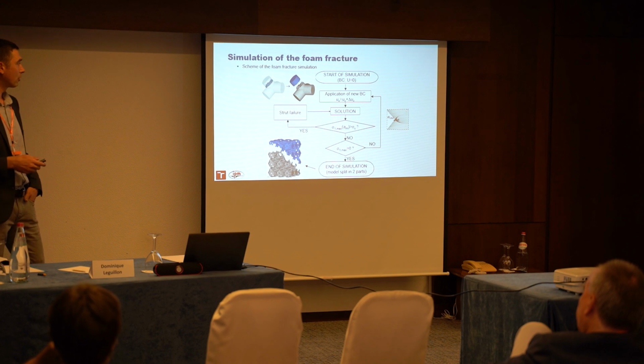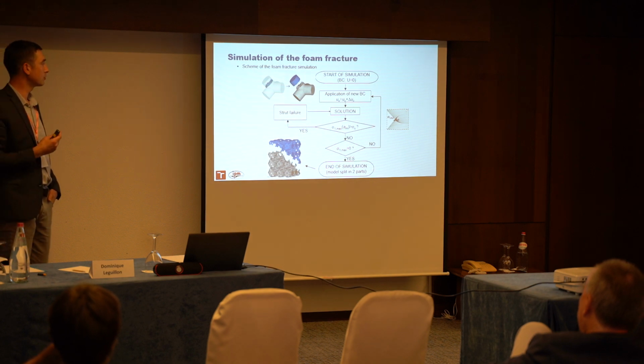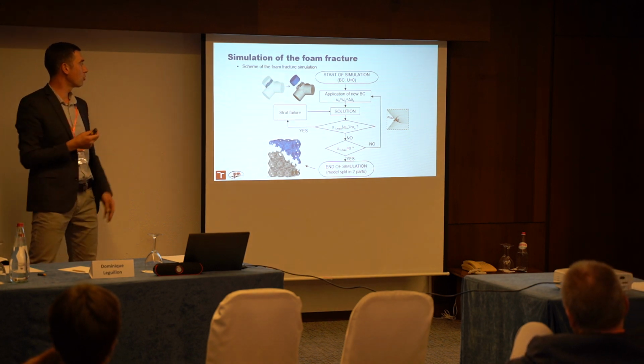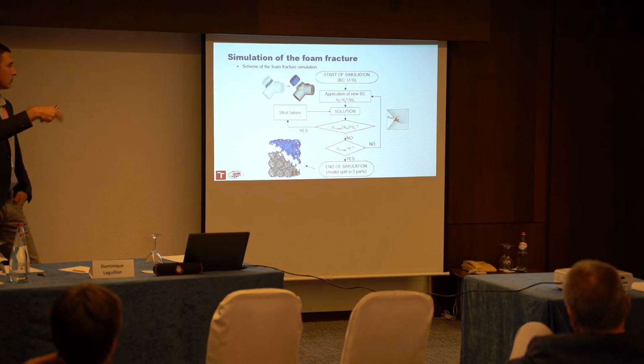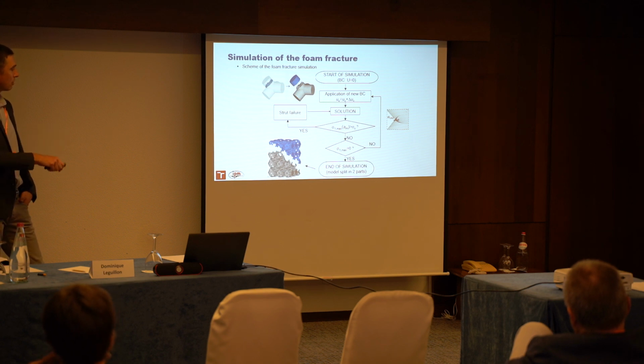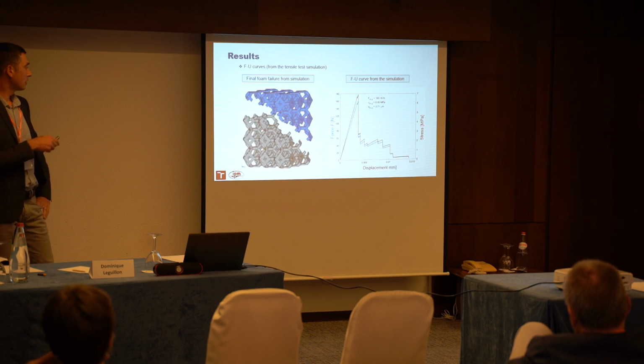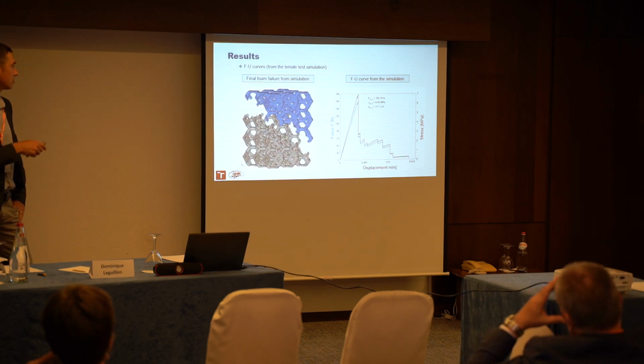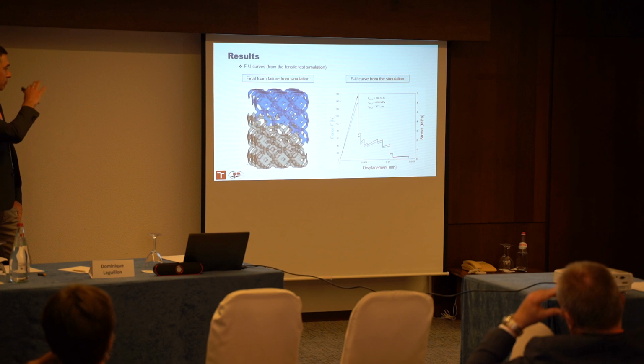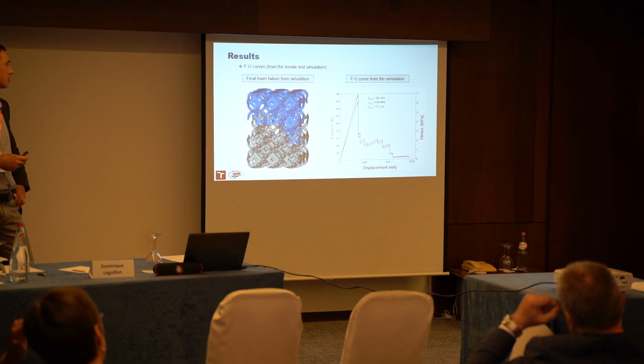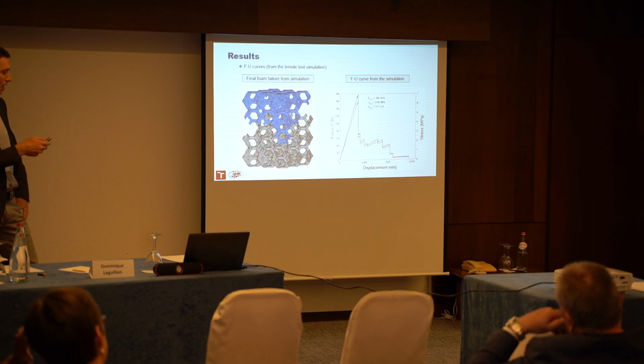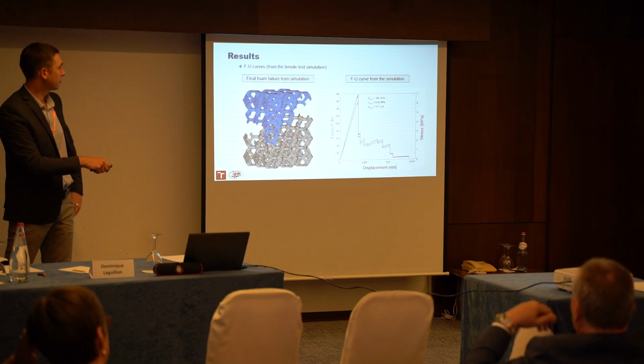If the failure condition was fulfilled, the strut was manually broken and calculated again. So in every step, only one strut was broken each time until the final fracture of the foam was received. And this is the final result. So this is the fracture surface of the foam compressed, and this is the result of the simulation.